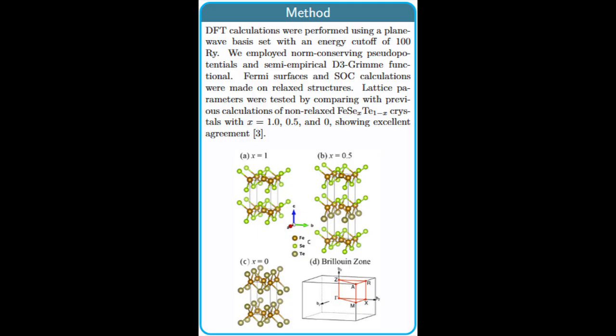Our calculations were performed in Quantum ESPRESSO using a plane wave basis set with an energy cutoff of 100 Rydbergs. We employed norm-conserving pseudopotentials and a semi-empirical D3 Grimme functional. Fermi surface and spin-orbit coupling calculations were made on relaxed structures. Lattice parameters were tested by comparing with previous calculations of non-relaxed iron, selenium sub X, tellurium sub 1 minus X crystals with X equal to 1.0, 0.5, and 0, showing an excellent agreement. Crystal structure and the first Brillouin zone are shown in the next figure.